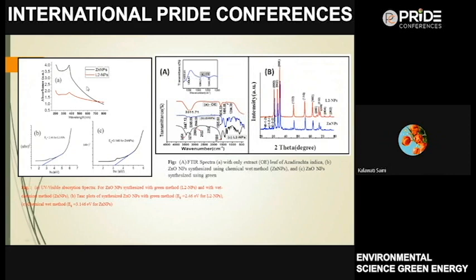And this is the comparative study regarding 2 ml of leaf extract used in the synthesis of zinc oxide. ZnO nanoparticle is the nanoparticle synthesized by the chemical wet method, in which we have used 200 millimole of trisodium citrate, 1 gram sodium hydroxide, and 0.2 molar zinc sulfate heptahydrate. These are the lambda max values for the green synthesized zinc nanoparticle L2, meaning 2 ml extract, with a band gap of 2.46 electron volt, and the zinc oxide synthesized by the chemical wet method shows a little bit higher band gap, that is 3.146 electron volt.